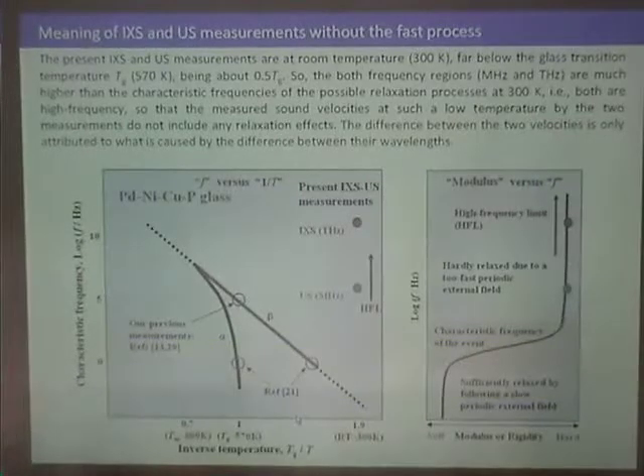Sorry, can I ask another thing that came up at the beginning of your talk? You call this beta process slow, right? But the mode coupling theory beta process, at least within mode coupling theory, actually has a time that diverges at TG. So it looks like it would necessarily be slower than your beta process. So I'm confused by the terminology. What you call the fast beta process would actually have to be slower than yours, because it has a diverging relaxation time.